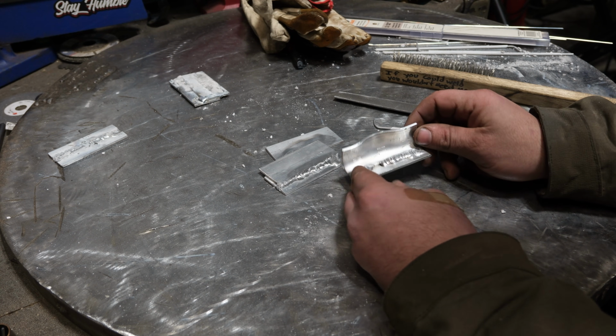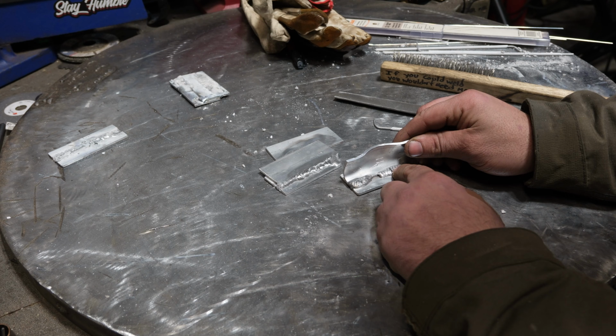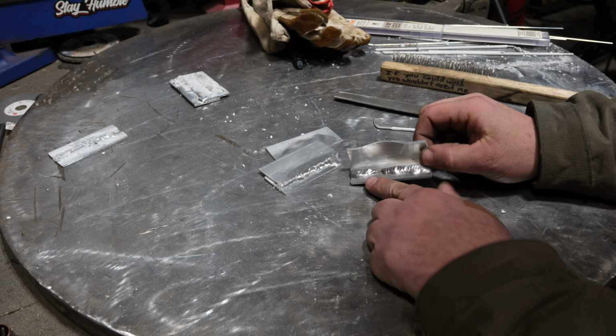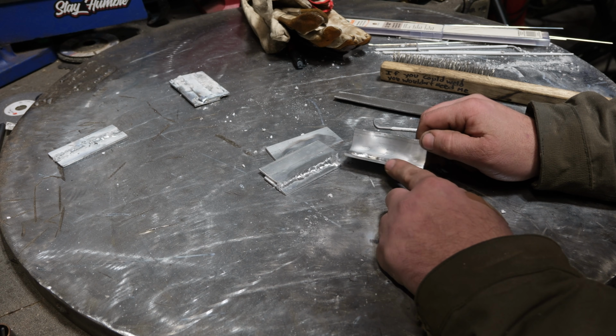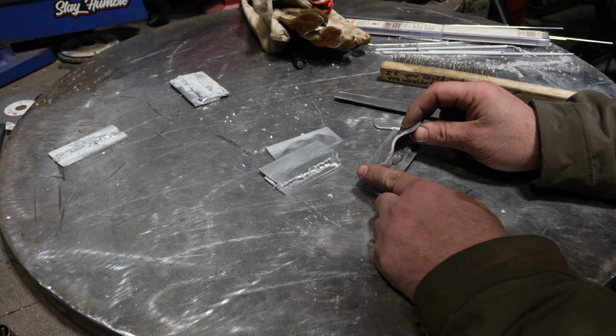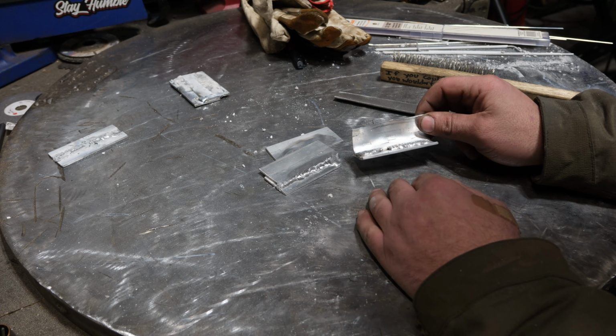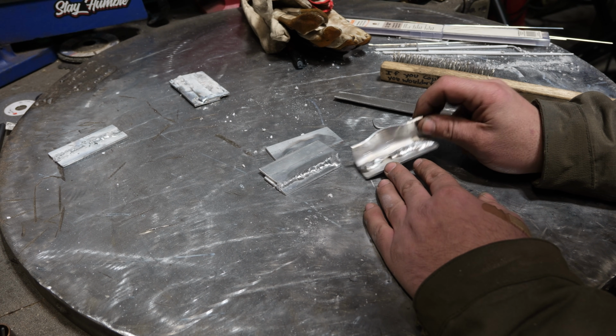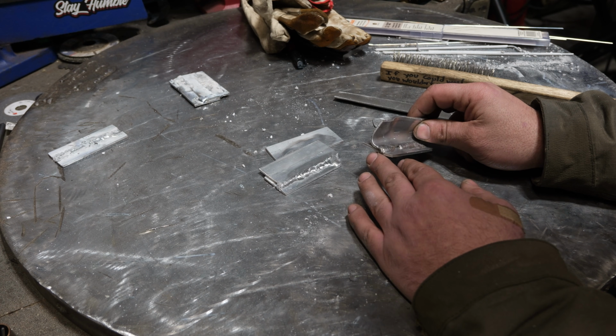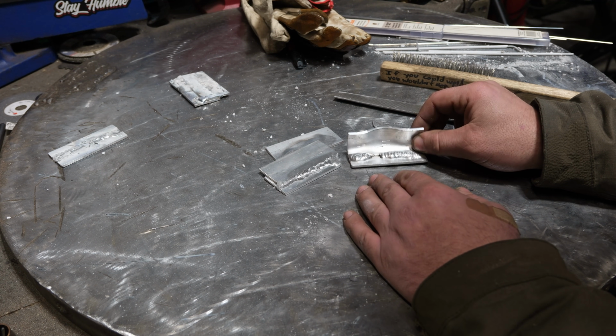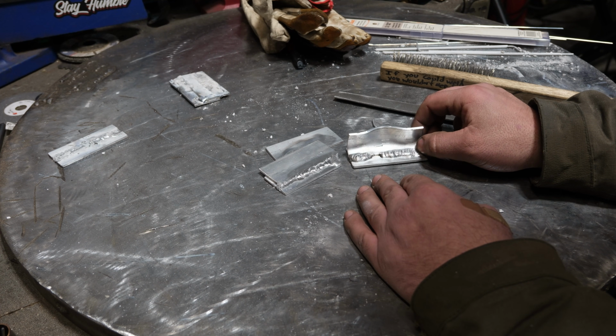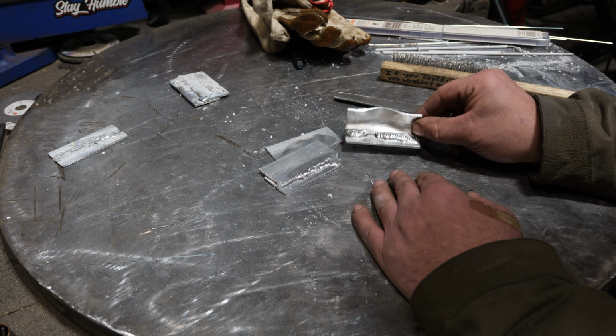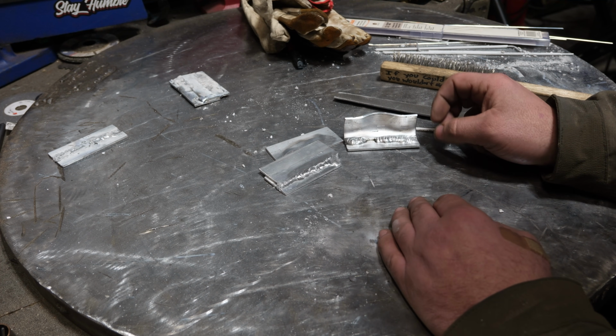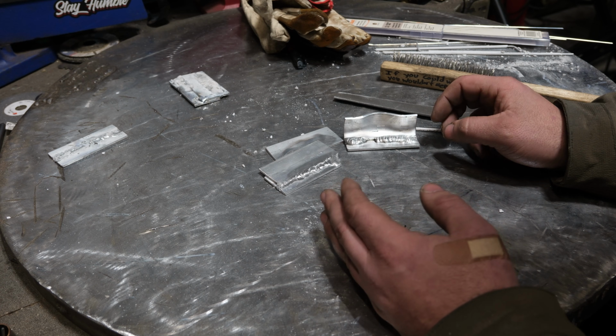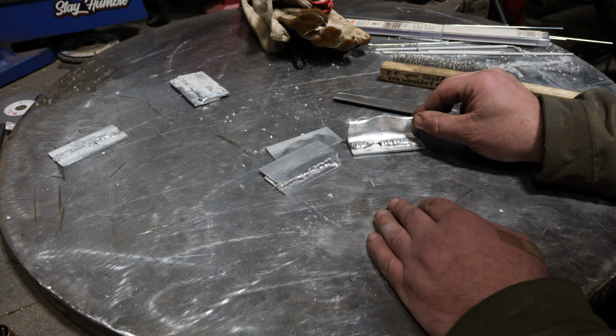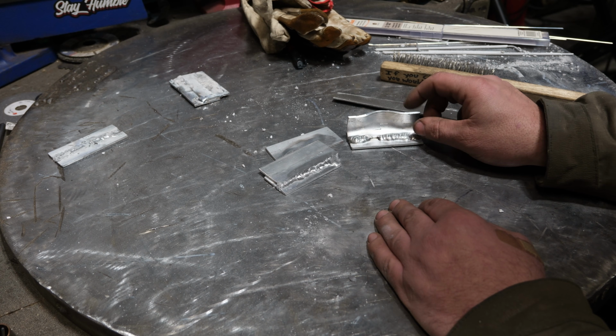Now, off camera, I decided, you know what, I'm going to bend this and see if there's internal weld porosity, and lo and behold, the weld held up, and I bent the base material, which isn't too surprising. This is 6061 T6 aluminum, and once you put enough heat into it, you more or less affect the temper or the heat treatment in it, and you weaken it near the weld. So it's not too surprising that the weld didn't fail, but I guess this bend test is kind of this whole deal in a nutshell, which is it will work in a pinch, but man, I wouldn't trust it. And if it needs to hold water, I definitely wouldn't trust it.